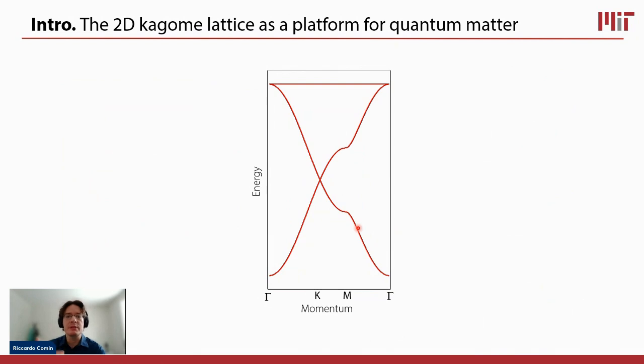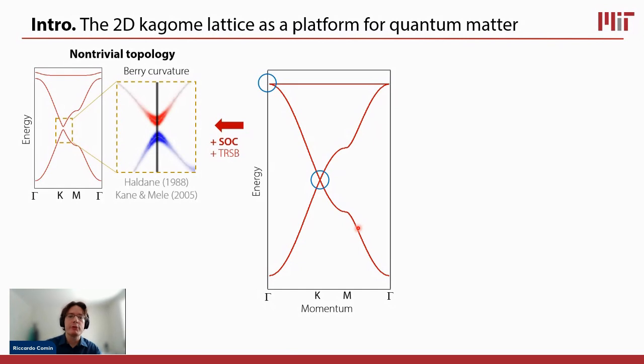So now if we start from this band structure and we start to play with it a little bit, we can see how this band structure can be used to realize both topological phenomena and electronic symmetry breaking. So if we focus on these 2 points of the band structure where different bands are touching each other, and if we activate certain types of interactions, for instance, spin-orbit coupling or spin-orbit interaction, and if we also break time reversal symmetry, what will happen at these special points of the band structure is that you will have a singular source of Berry curvature, which is like a monopole of the pseudomagnetic field that is entirely due to the quantum geometry of the wave functions.